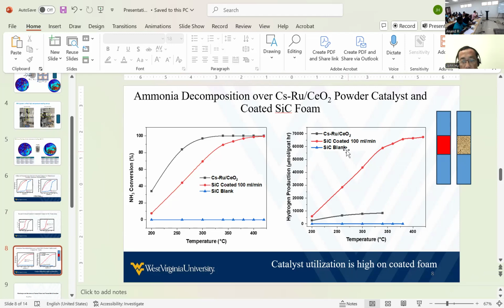Because if you correct everything based on the productivity, based on the active ingredient, this is much better than this, which is the non-coated. So that means you fully utilize the catalyst on the monolithic, whereas in here you do not fully utilize the catalyst. Some catalyst may not be active; it's a gas that goes through, but here you fully utilize. That's why productivity is very high. So this is the reason we go to monolithic, not only for the heat transfer, not only for the pressure drop, it's also for the utilization of catalyst. Make sense?